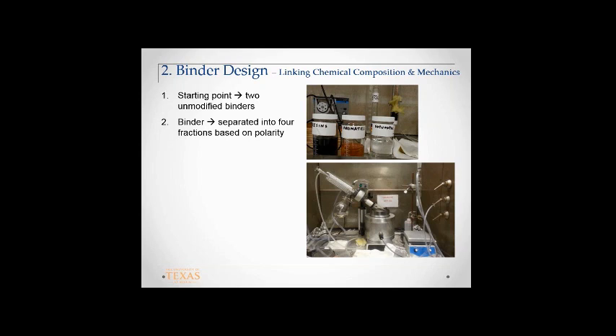Here is an asphalt binder broken down. These are the saturates, clear. They are in solvent, although if you evaporate the solvent, you'll be left with 1 or 2 grams. The solvent is transparent or colorless by definition, since it's a high purity solvent. So you can see the saturates are clear. This clear, transparent, oily stuff is in the conventional binders we use for road applications. And these are also the least polar.